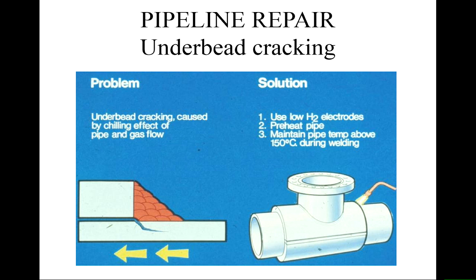And these defects parallel to the surface sometimes are invisible to the radiography, because if you imagine the radiography going through, you wouldn't actually see that, but it can be opened up by welding onto the surface. So there are special welding techniques that you would tend to use under those circumstances, largely to reduce the chance of hydrogen embrittlement or hydrogen-induced cracking in these systems. Use low hydrogen electrodes, preheat the pipe, and maintain the pipe temperature above 150 degrees C during the welding process. So that's the interpass temperature is above 150 degrees C.